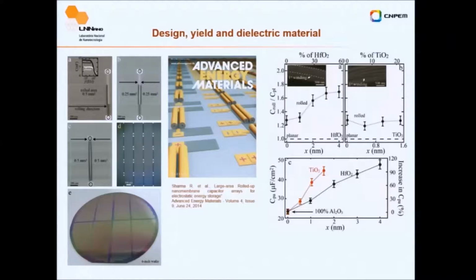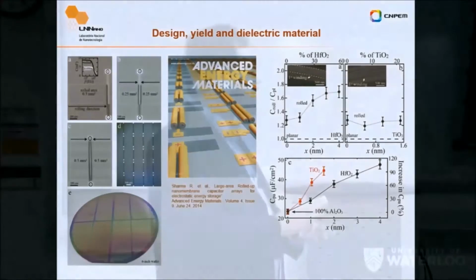We also identified, and this picture simply shows, the ratio between the capacitance of the rolled device and the planar, and how the amount of hafnium embedded in between aluminum oxide changes the capacitance. So basically this will give you a message on how much the material has an effect on the rolling, whether it increases the capacitance or not. So we tested a lot of titanium oxide and hafnium embedded in aluminum oxide, because if you use titanium oxide or hafnium directly, the leakage current at 6 nanometers is really huge. So then you make a sandwich of aluminum oxide, either titanium or hafnium, and aluminum oxide again. So you play with the quantity of those materials.